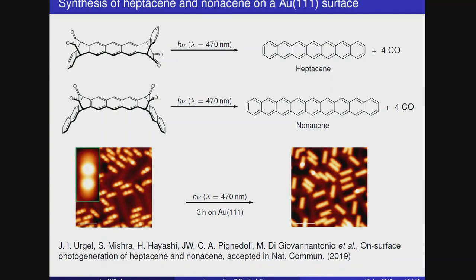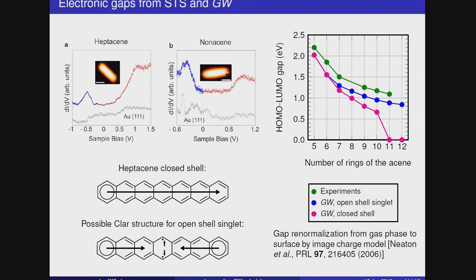The problem until now was always that these molecules are very unstable for long acenes. Recently at MPI, they have been able to synthesize heptacene and nonacene on a gold surface by some fundamental chemistry reaction. And now they also can measure the HOMO-LUMO gap of these molecules by scanning tunneling spectroscopy. They make an experiment and they can probe here the HOMO level and the LUMO level. Of course it's not extremely well defined, but they can measure the distance between HOMO and LUMO and in this way they can get the HOMO-LUMO gap. One can plot the HOMO-LUMO gap as function of the number of the acene rings. So you see here, this is the measurement from MPI and this is the other one. Also last year, luckily, the acene with 10 and 11 rings was also synthesized on the gold surface, so there are also points.